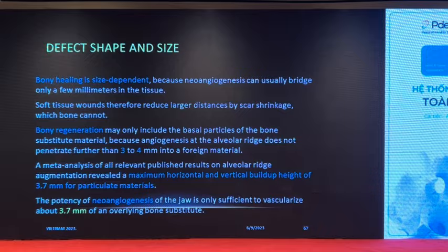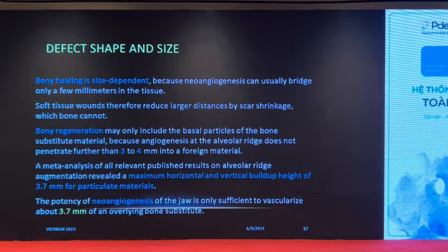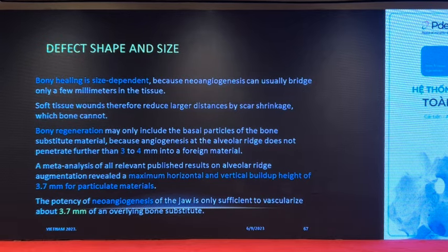So we can put inside many granules, but there will be no results. We can get only 3.7 millimeters of new bone. The potency of neoangiogenesis of the jaw is only sufficient to vascularize about 3.7 millimeters of overlying bone substitute.